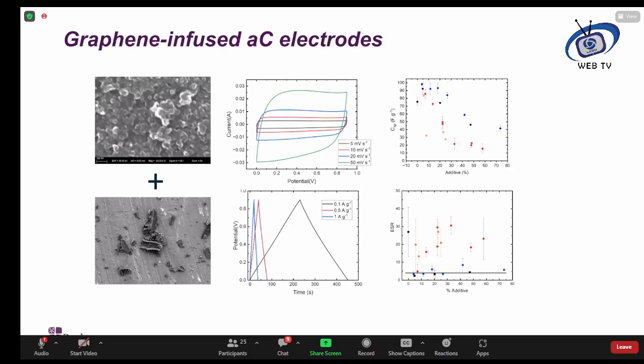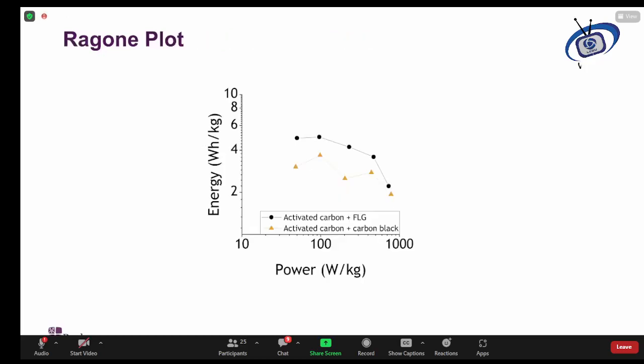So we can therefore investigate this a bit further by looking in detail at comparing this broad distribution of few layer graphene to the activated carbon on a Ragone plot, where we plot the energy density in watt-hours per kilo against the power in watts per kilogram. And you can see over a variety of discharge conditions, so these are a series of discharge currents ranging from 0.1 to 1 amp per gram, that if we infuse activated carbon with a broad distribution of platelet sizes of few layer graphene, we get an enhanced performance compared with a standard carbon black.